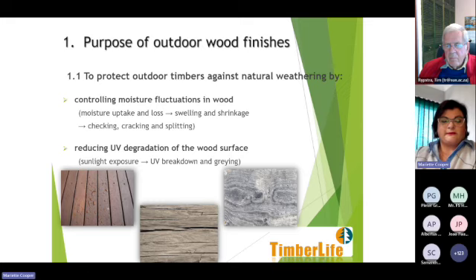Excessive swelling and shrinkage cause movement, and if not controlled, this can cause the timber to check, crack, and also split. When we talk about reducing the UV degradation on the wood surface, that occurs when the timber is typically exposed to sunlight. And if not controlled, the UV breakdown and the graying and aging of the timber will occur faster than if it was sufficiently protected.